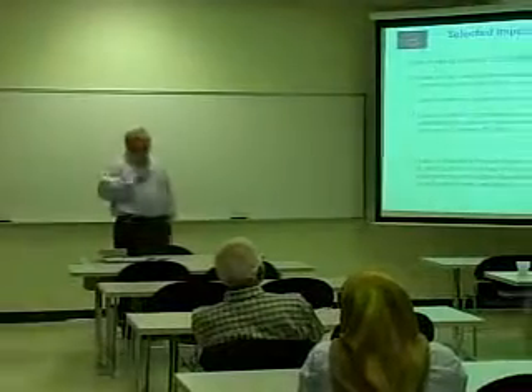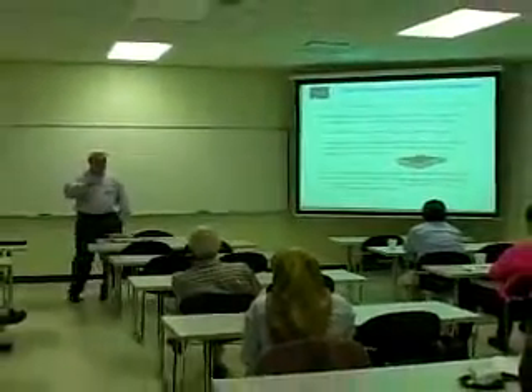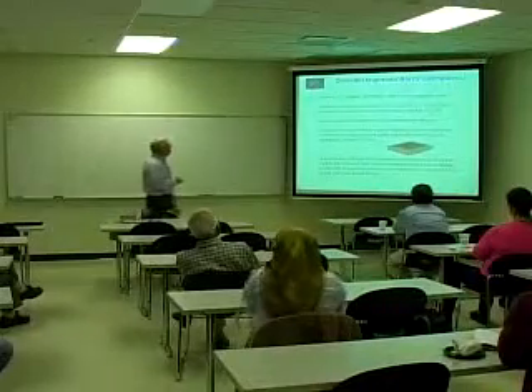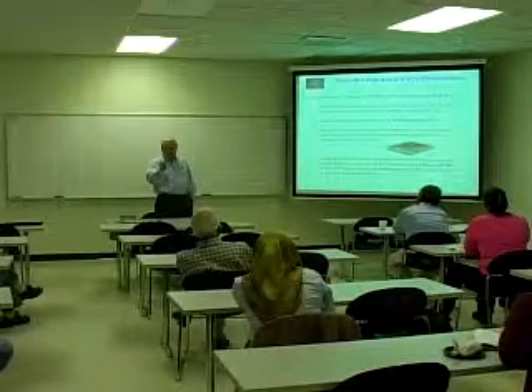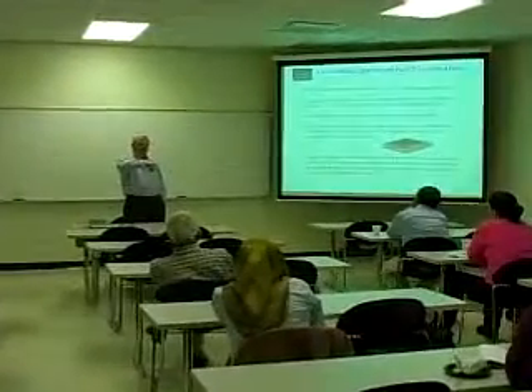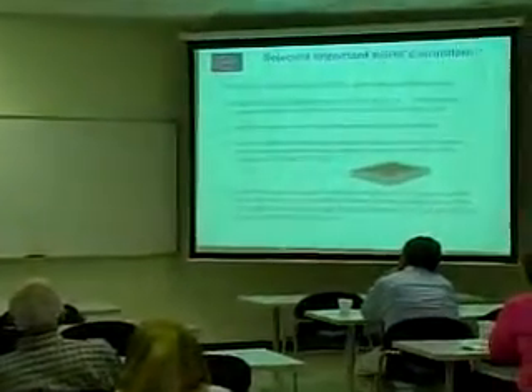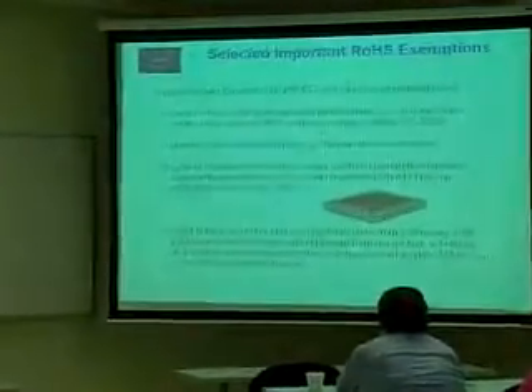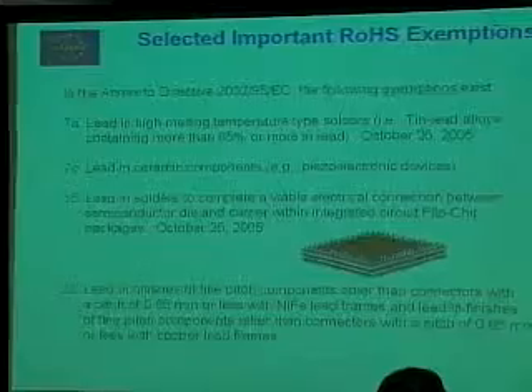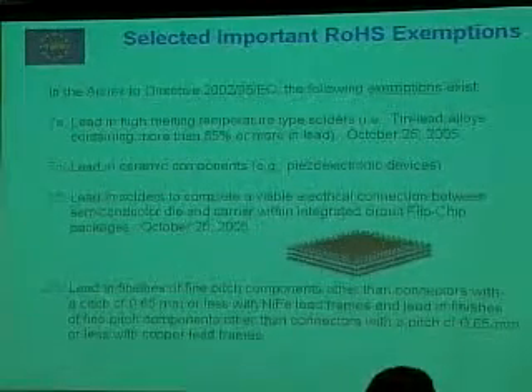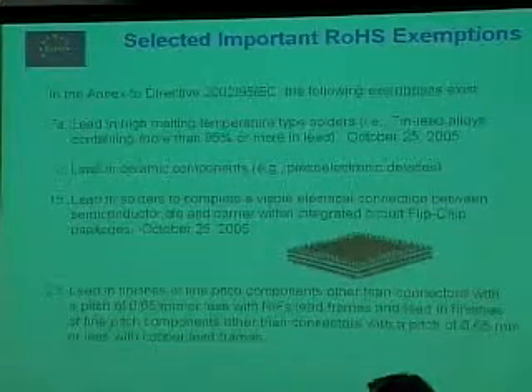So just to give you an example of some of the exemptions, and incidentally, lead acid batteries are not forbidden, but they must be recycled. So there's an exemption, but that's not under RoHS at this point. Okay, so for example, one of the exemptions is that in, say, flip chip on an integrated circuit, you put solder balls on it, you flip it over, and you attach it to the package. It turns out that you want a higher temperature solder to do the solder balls on the flip chip. So they have made an exemption. They allow high lead solders to be used. And in fact, 90-10, 90% lead, 10% tin. 93-7 is also used for flip chip. So there's an exemption.